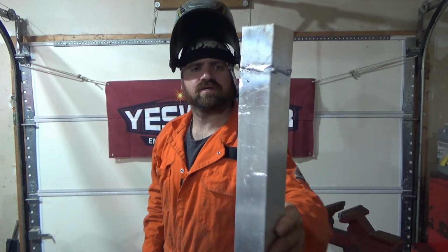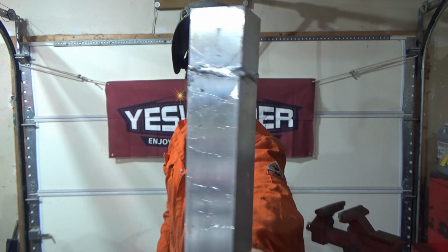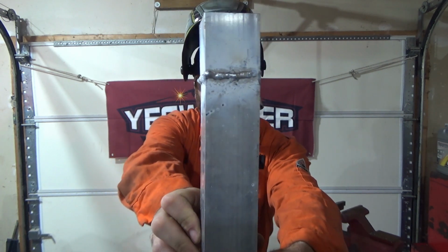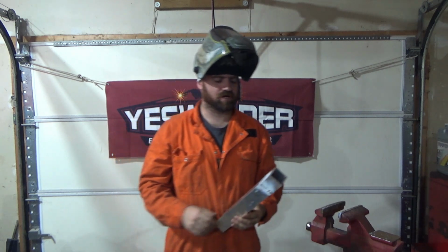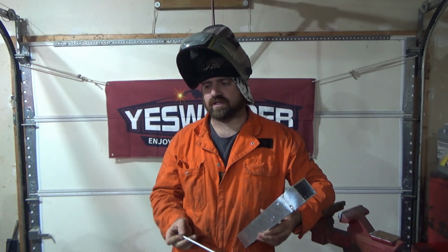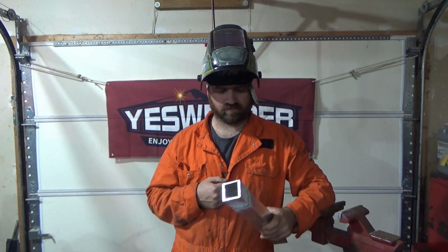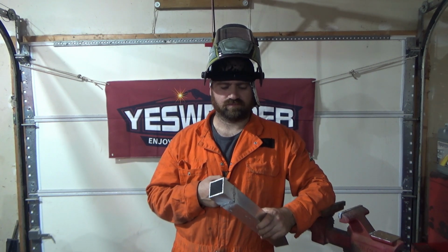So that's my aluminum weld there. This is not an easy thing to do. You could see how bad I was struggling. And the slag that's left behind is quite ugly. These welding rods get taken up very quickly. I'll go through 2/3 of this rod on one side of this tubing. But this is not a fun thing to do, so I really don't like to do it. But it's doable.